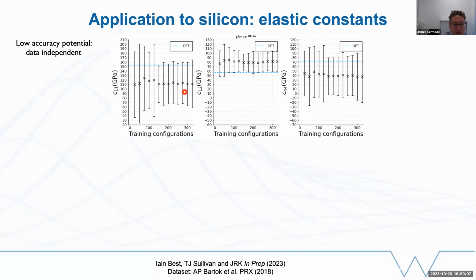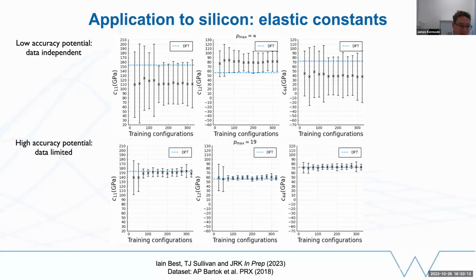So these calibrated error bars show you that the predictions from your model are not very accurate, and they do cover the true result. If we make our model more accurate, we put more degrees of freedom into it, we then get into a data limited regime, where as we increase the amount of data, we get a step from models which are insufficient to models which are good enough, and where the error estimate is sufficiently accurate as well.